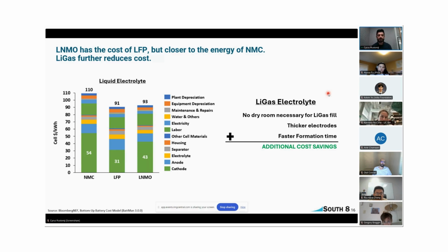I won't get too much into a few of these items, but we can eliminate the need for a dry room when we're filling the liquefied gas electrolyte into our cells. That's because we seal the cell prior to our electrolyte injection. We just have a tiny little hole, which through some mechanisms is sealed until the injection process starts. And so we can eliminate some of that dry room requirement. I just discussed using thicker electrodes to lower the cost. And also we have demonstrated faster formation times. Whereas today a lot of people are forming the cells in days, not hours, South8 has already demonstrated we can form our cells much faster.